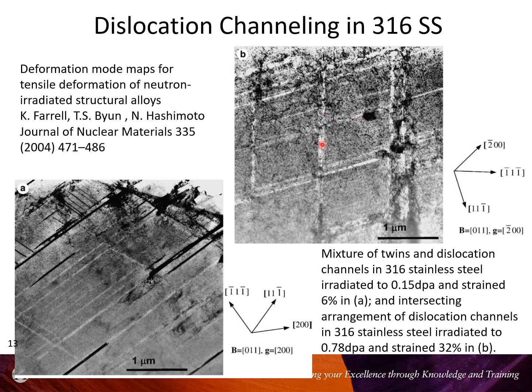So by and large, if you read any of the papers, they'll often say, well, we see a mix of channels and twins. So just making it very clear to everybody that you have to be careful that you don't mistake twins for channels. But you can often, I think easily, tell when you have a twin simply from the contrast, because the channel itself should not change the diffraction contrast. There'll be a contrast difference simply because there are fewer loops in the channel, but if you look at the actual matrix and the scattering of the electrons, that should not change. Oh, sorry, it will not change in the channel, but it will for a twin.